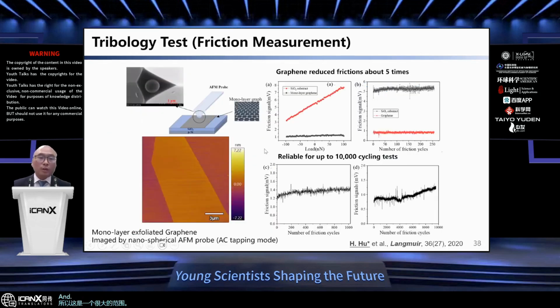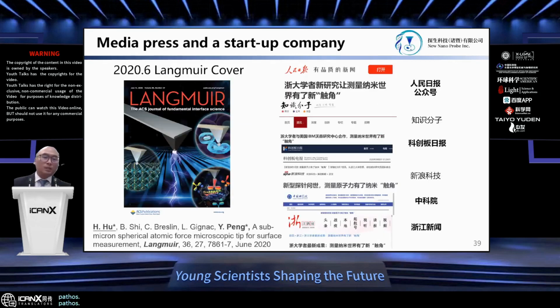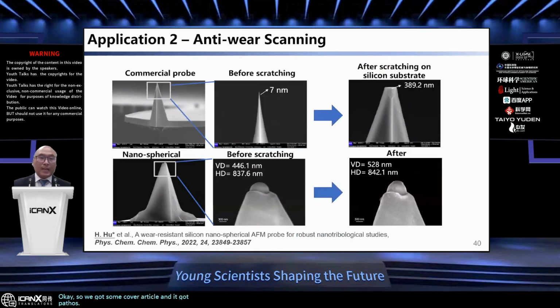What's more interesting is that this silicon nanosphere is super robust. It's monolithic. We repeated cycling about 10,000 times, and there's nothing bad. We got a cover article and some media press. Looking at the wear property, this is a commercial probe. After about 1 meter of scanning, the commercial probe becomes 380 nanometer. You have no idea where your measurement will be. But for our nanospherical probe, we apply the same normal force and scan the same distance, and we only get a little bit of accumulation due to tribochemical effect.